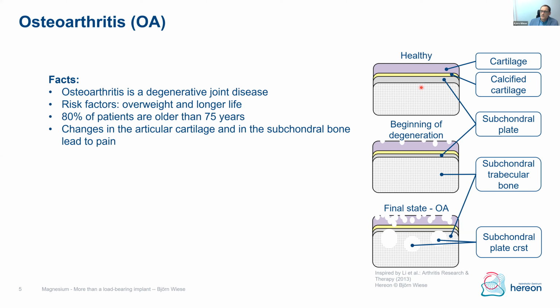And what does it mean? If we look here at one bone or one joint side of a healthy bone, we have a layer structure of cartilage, calcified cartilage, subchondral bone plate, and trabecular bone. This is the spongy part in the center of the bone. And when osteoarthritis starts, we get degeneration of the cartilage. There are some pits, and it's no longer flat like it should be. Also this plate gets thinner with time until the final stage. There, the number of defects increases up to voids inside this subchondral bone plate and also the trabecular bone.